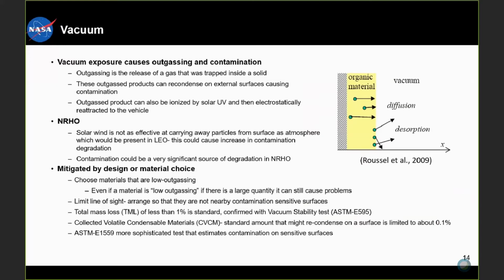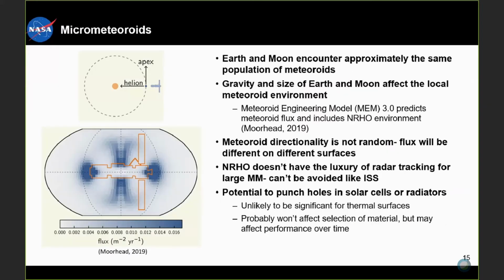So some of the things that you can look at when talking about outgassing of your materials: there's the total mass loss, or TML, of less than 1% is standard, and that's confirmed with a vacuum stability test. There's also collected volatile condensable materials, or CVCM. This is the standard amount that might recondense on a surface, and it's limited to about 0.1%. And then ASTM E1559 is a more sophisticated test that estimates contamination on sensitive surfaces.